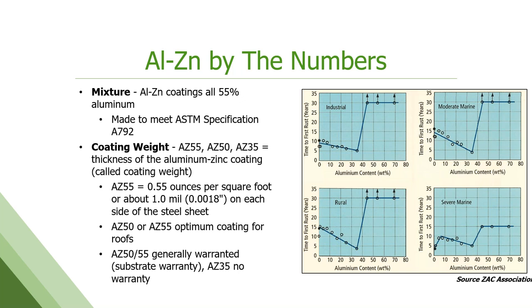AZ50 is the other most common weight now, and is probably the majority of what we see specced and used. It's 0.0016 inches on the surface. The AZ50s, the AZ55s, and higher, we do see higher coating weights for heavy industrial use, pipe usage, that kind of thing. And those will generally be warranted for corrosion, but anything less than that is not. The AZ35, which is a low coating weight, will not be warranted. And you also cannot use the name Galvalume with it, even if you have a license, because it's just not going to offer the same protection.